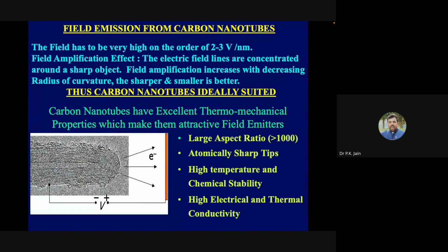As I told you, this is a field emission of carbon nanotube. The field has to be very, very high, in the order of 2 to 3 volt per nanometer. And because of that, if a material itself does not have very good properties, it will have a lot of chemical activities. So the inherent material should be chemically resistant, high temperature stable, with a large aspect ratio and an atomically sharp tip. All these things put together, carbon nanotube is the ideal material which acts as a field emitter.